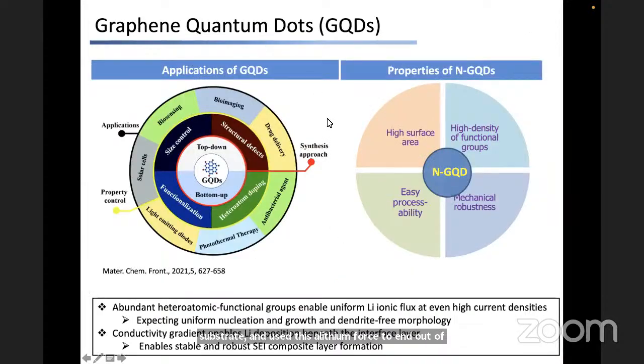Okay, so graphene quantum dot is not a new material. In display and optical materials it is a pretty well-known material, very small particles, which can come from the carbonization or hydrothermal process of biomass, which gives us very small nitrogen-doped dots. Under UV light we can get a specific light color, and in the TEM you see the very small size, typically a few nanometer sheets, and blue light emission is possible. So the typical size is 2 to 5 nanometers, a very well crystallized material.